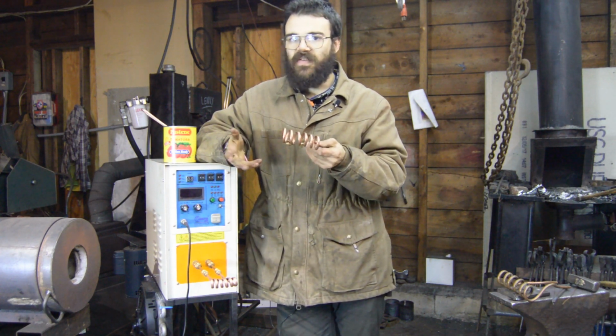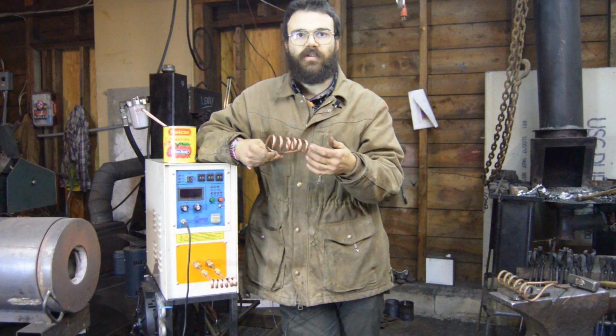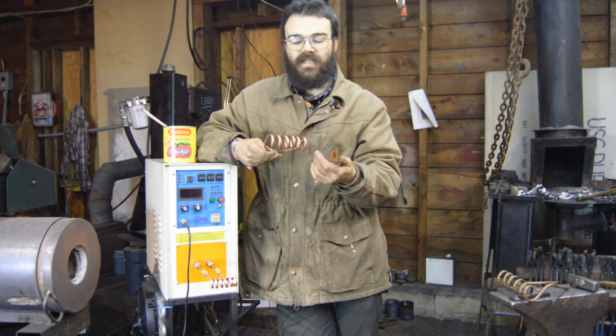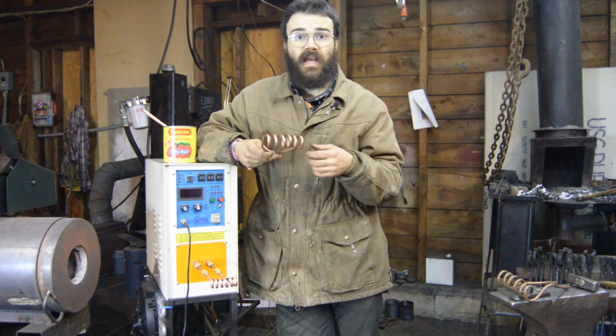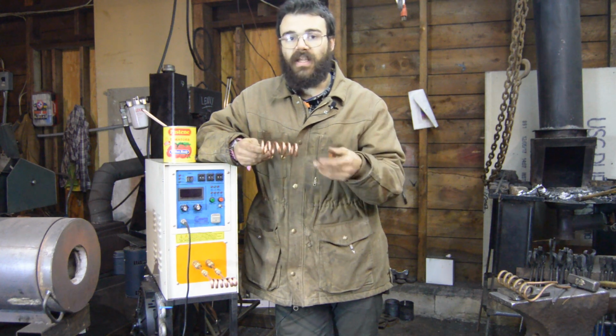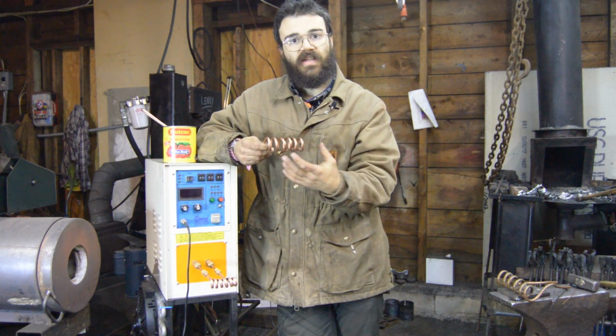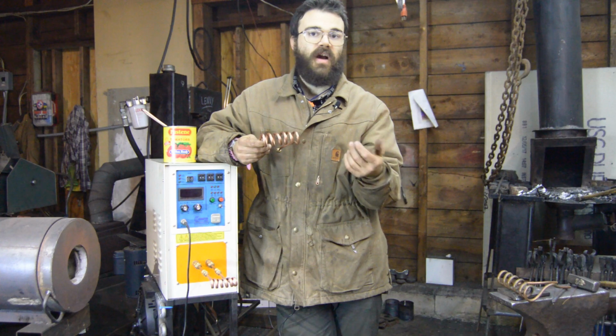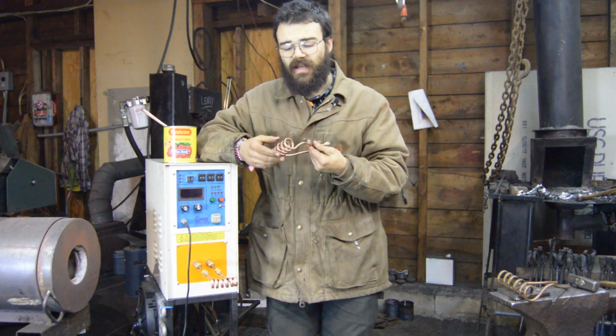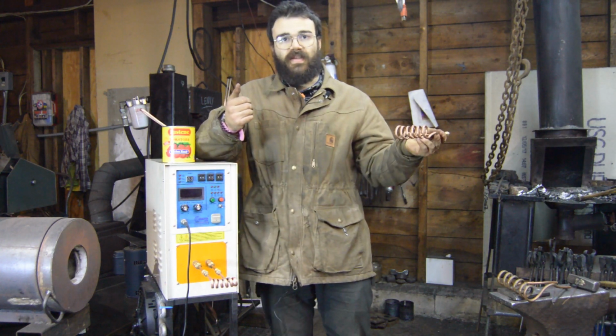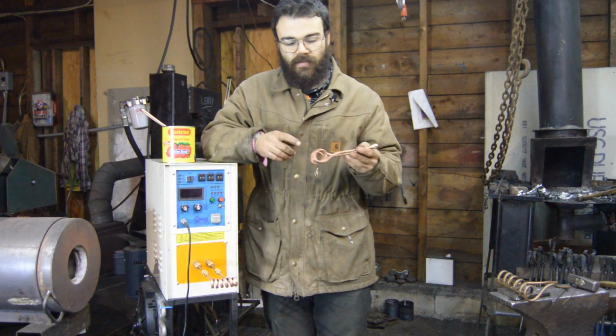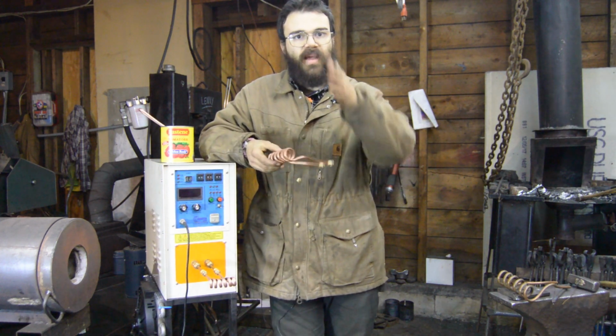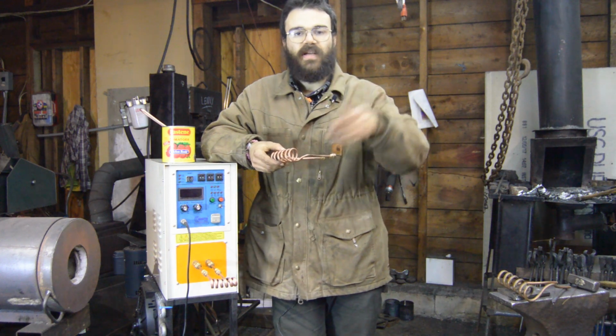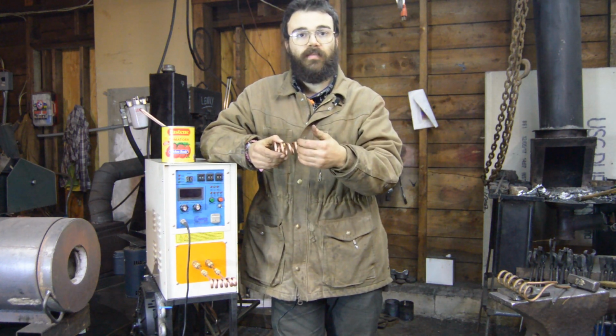That being said, it's not always feasible, and for a coil like this for general purpose heating, I can easily get material up to 1700, 1800 degrees very easily with the spacing, and the spacing allows me to get a longer heat with less copper used. That being said, if you used a huge spacing, like 3 or 4 times the tubing diameter, you'd notice sort of a banded heat. So you'd have hot spots and cold spots right next to each other, and the hot spots would line up with where the coils are.